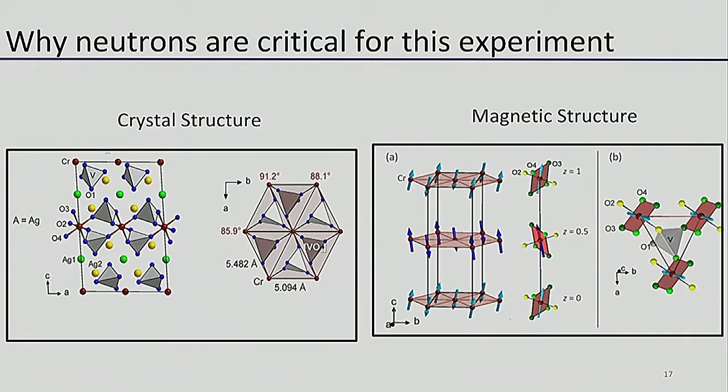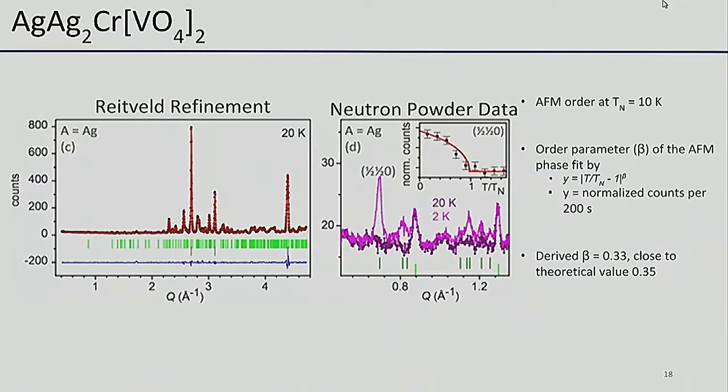In fact, they kindly took the octahedra animation or artistry out of these. So there's the chromium, and there are the 6 oxygens that it's connected to. But you can see this plane, and they're trying to highlight where you have the oxygens either closer to each other or farther away. That's our distortion. And depending on how that is hooked up to your vanadium, that'll be where your spin is going. And these spins are able to interact with each other. They're not facing each other. They're coming out of the plane at us. So we have 2 going down and 1 going up. We have an antiferromagnetic long-range order.